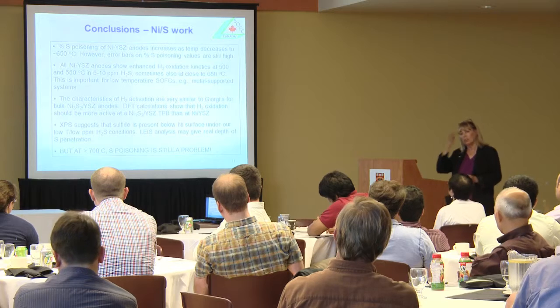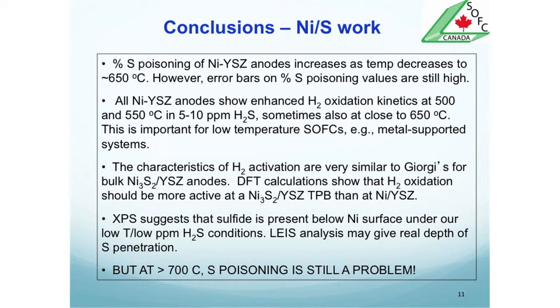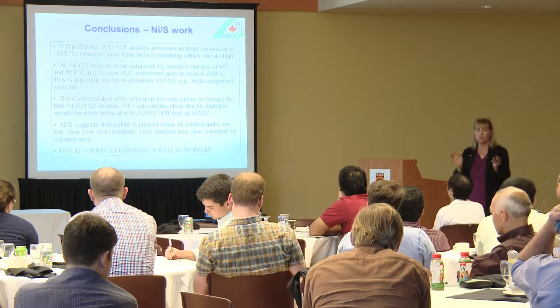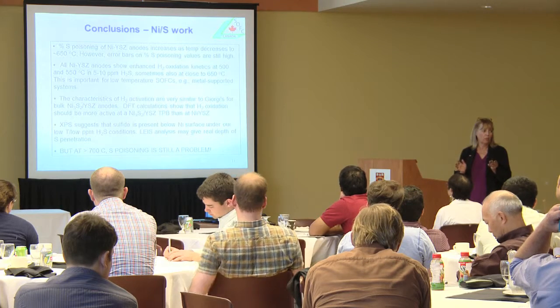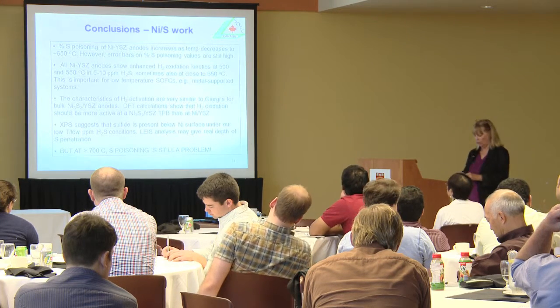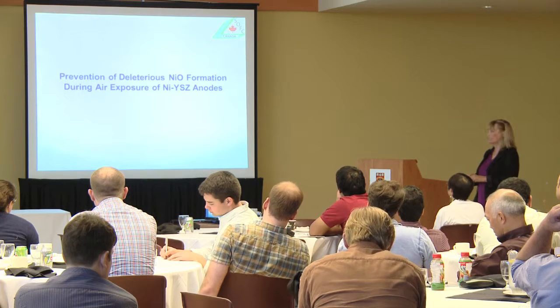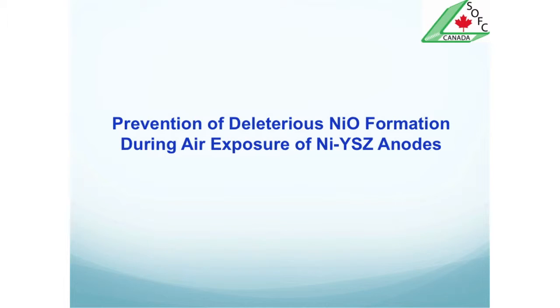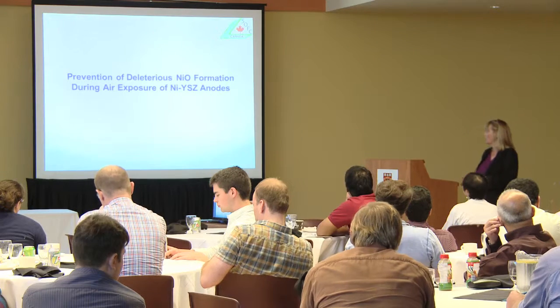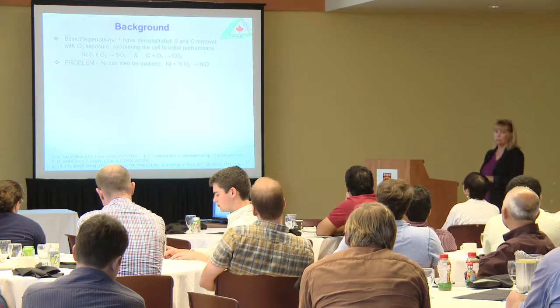Okay. But I wanted to turn now to try to link the sulfur and oxygen work. So, in fact, as I said with the first bullet, if you're up at those normal operating temperatures, sulfur is a problem. And the question is, how can we remove it? And so as I said earlier, we thought about, can we use oxygen to kind of strip it off? And so let's look at this issue with stripping off sulfur with oxygen.